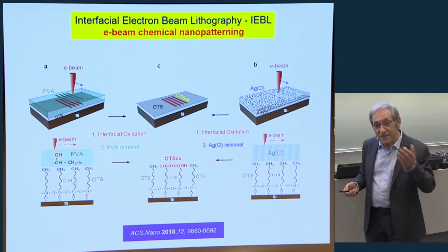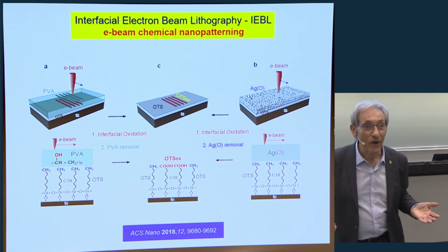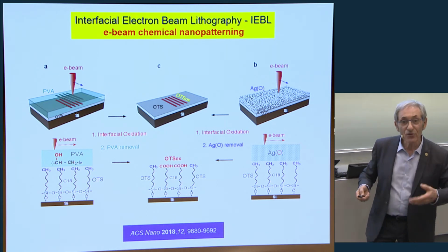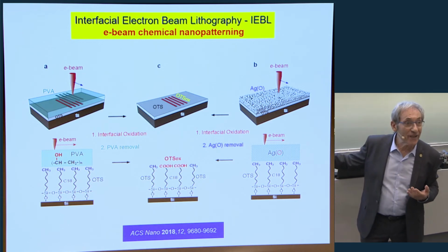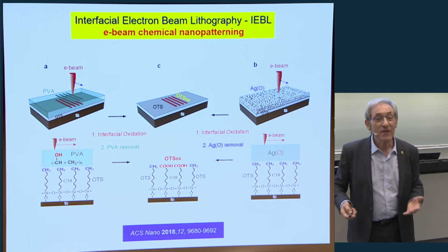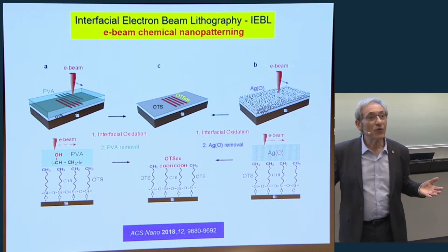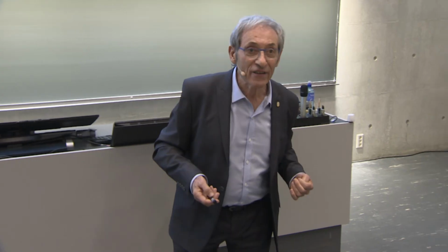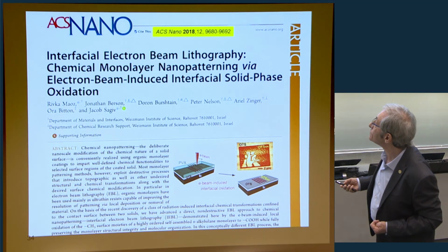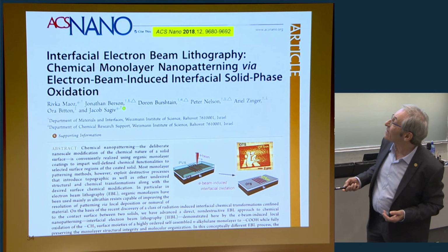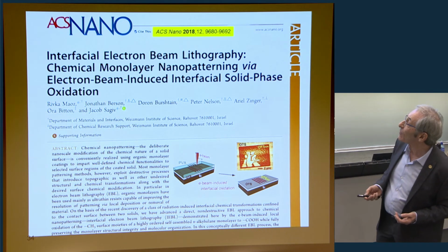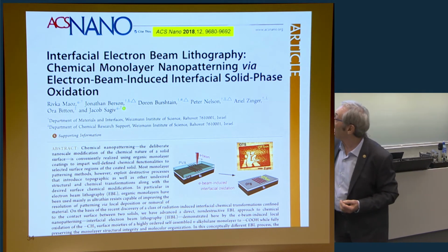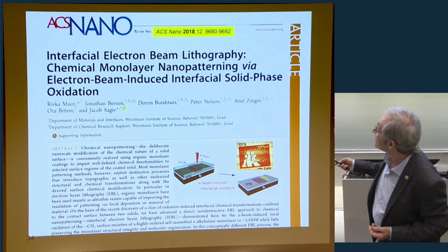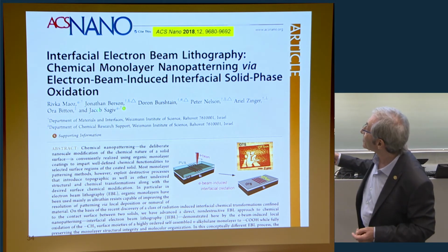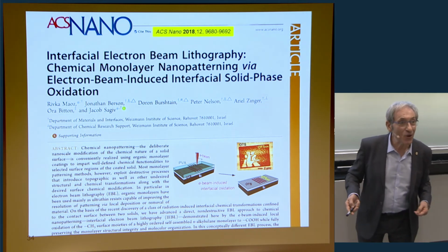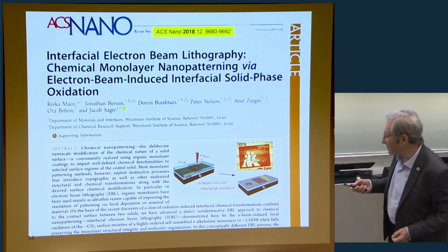Now, since the electron beam machines are perfected for patterning, while the AFMs are produced mainly for imaging, the capabilities that you have for writing with electron beams are much more developed than with the AFM. The AFM is limited to a scan usually of the order of 100 micrometers. You'll see that with the electron beams you can write centimeters. So this is the paper that we published on interfacial electron beam lithography, chemical monolayer nanopatterning via electron beam-induced interfacial solid phase oxidation. And I should mention that three of the first authors, Rivka here, Jonathan and Doron, participated in the events in Oslo this week. So, to give credit to the people.